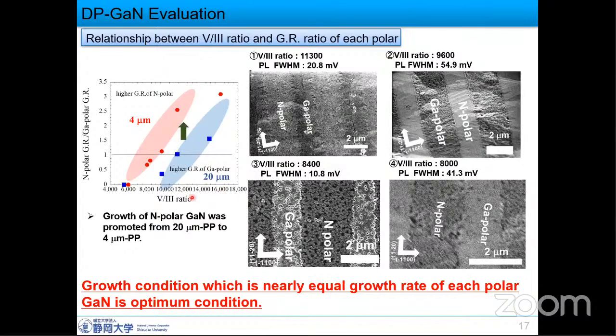So this discussion is going to be talked about on the next slide. And from PL measurement, growth condition around V/III ratio 9,000 is the best condition for DP GaN. Each polarity growth rate is nearly equal at V/III ratio around 9,000.